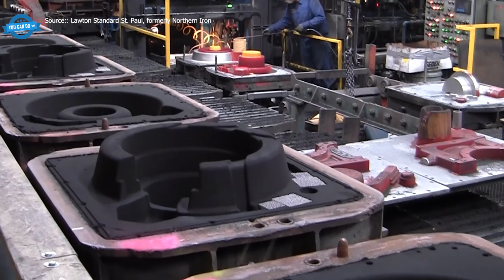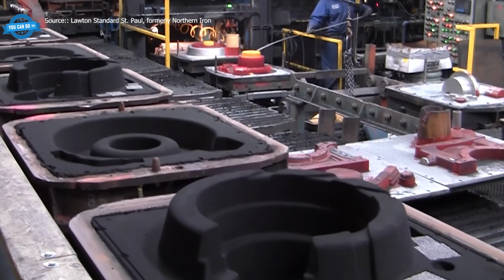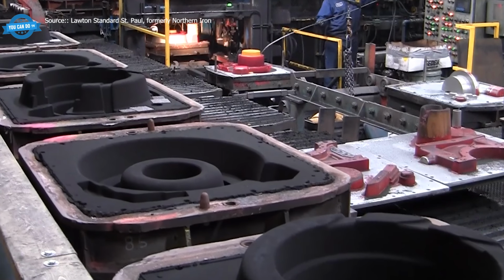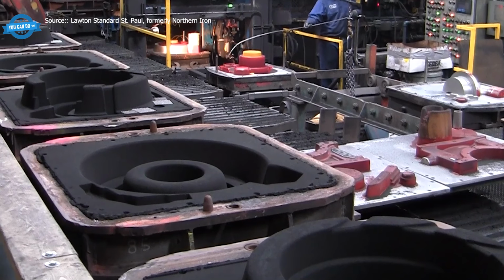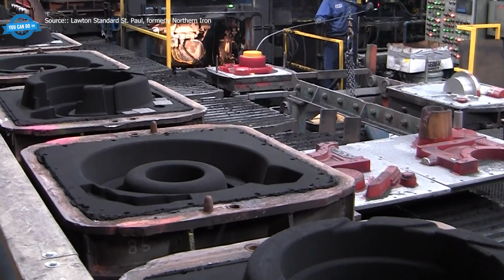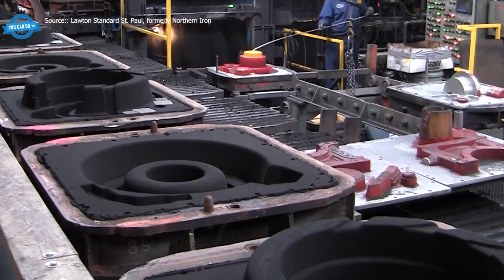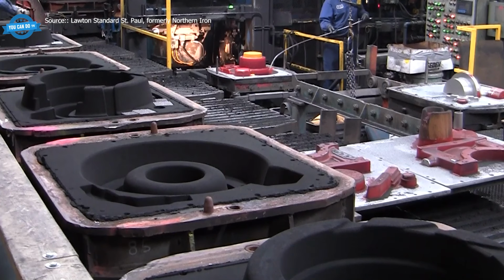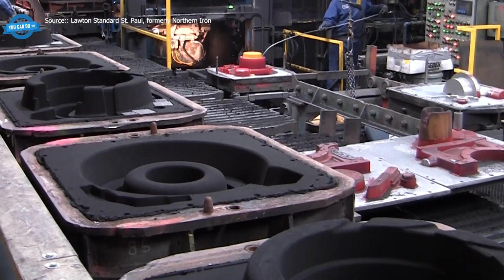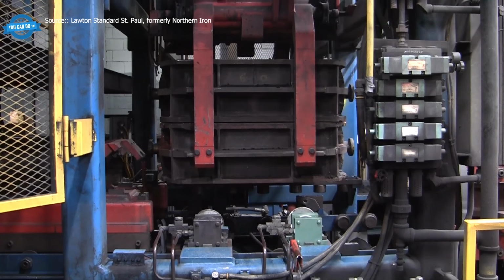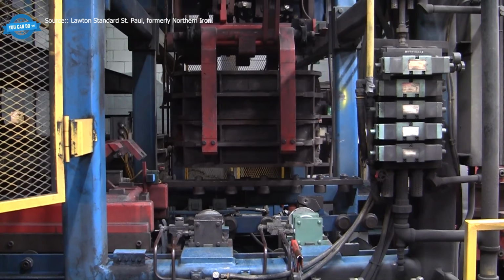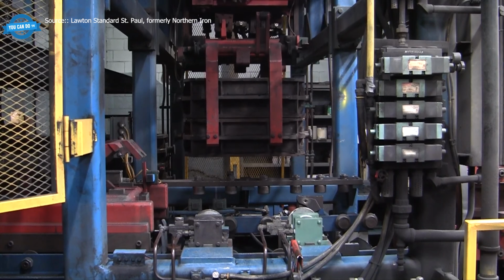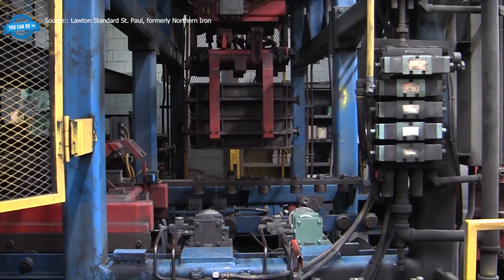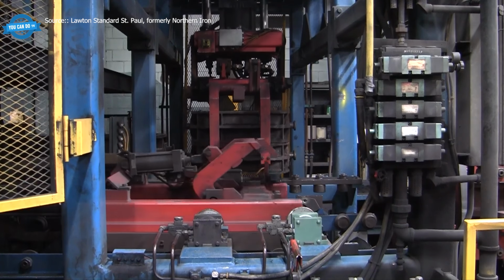Molten iron flows from the ladle into each mold in sequence, with a worker checking pouring temperature between cycles. The whole point is to make identical castings, one after another, without variation creeping in. Iron castings up to 250 pounds, brake rotors, gearbox housings, pump bodies, differential cases, come off these lines in numbers that keep entire industries supplied.